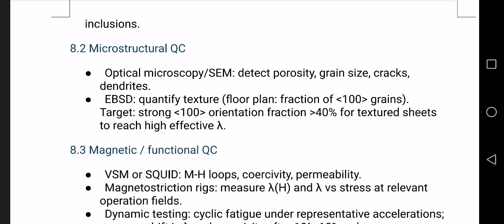Electron backscatter diffraction, EBSD, is very important for Fe-Ga alloys. It tells us grain orientation, texture strength, and its target is 40% grains oriented along the 100 direction. This gives high effective magnetostriction. Electron backscatter diffraction has a main purpose of orienting almost 40% of grains towards the 100 direction.